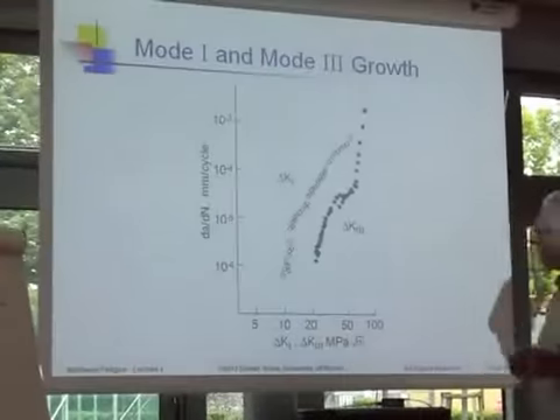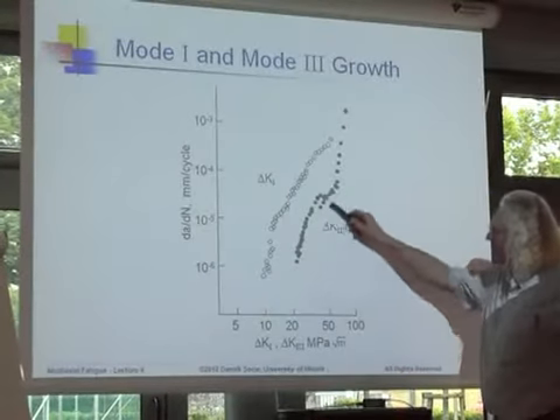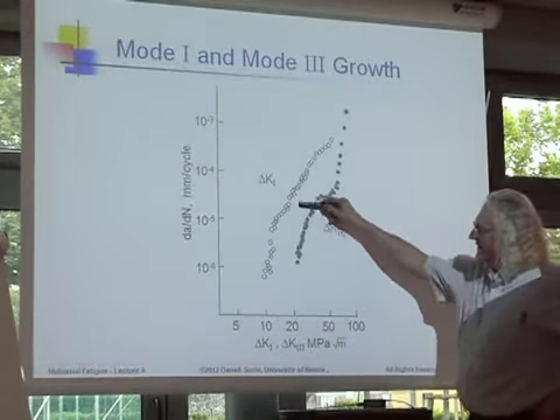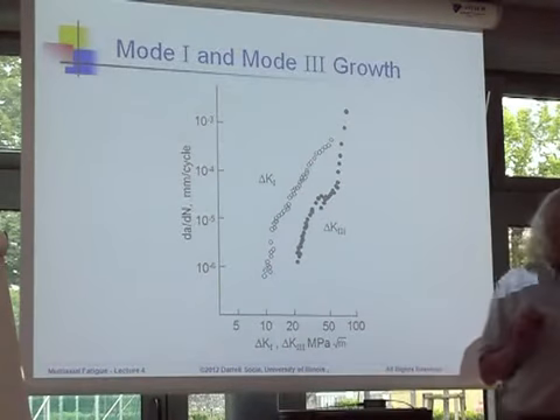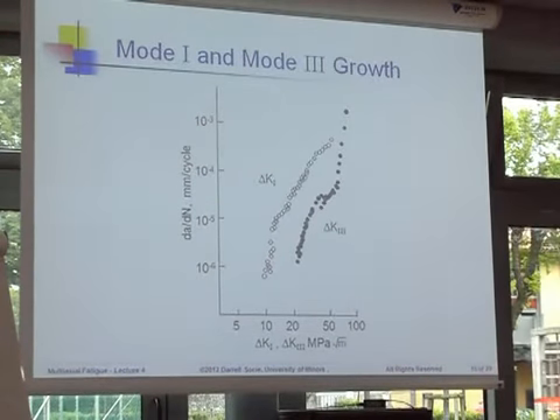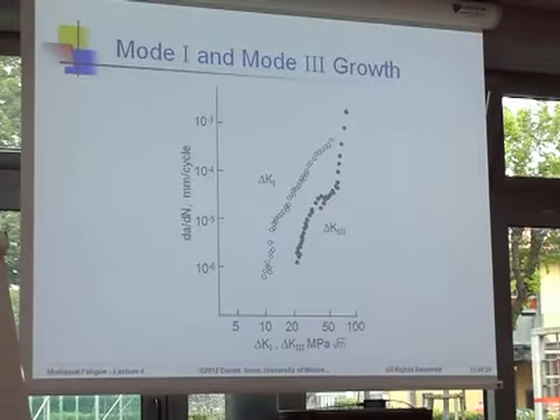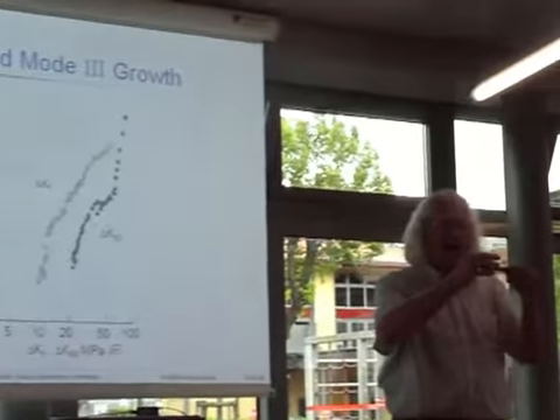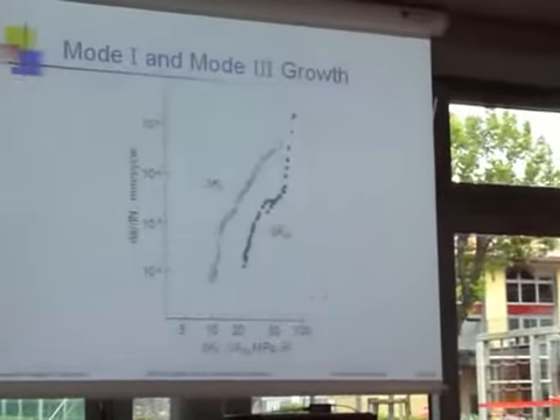And so most of the data that you find always shows that the mode 3 crack growth rate is an order of magnitude slower than mode 1. Well, if that's a slower mode of crack growth, then it's not a surprise that a material would try to turn and change direction and go from mode 3 to mode 1 if it can. And that's exactly what you find in service. I'm going to come back and talk about the mode 3 growth again in a few minutes.